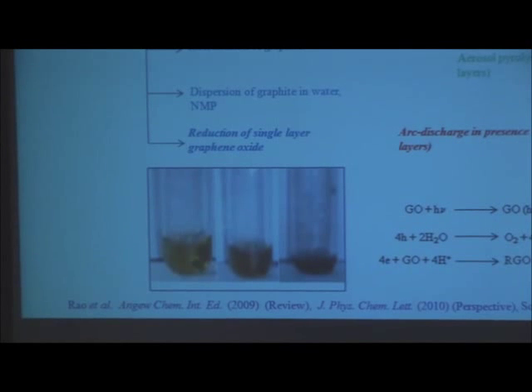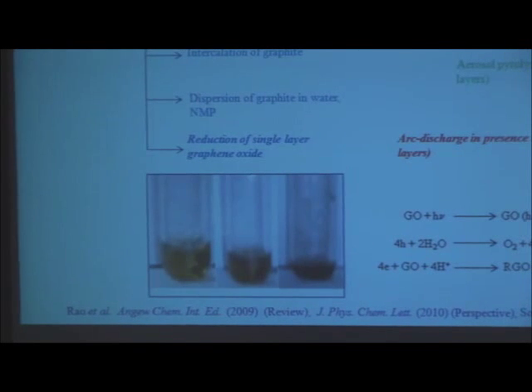It's all terrible. I didn't like it. So I was amazed when we found this one. What we find is you take graphene oxide, it's yellow, brownish yellow in color. We just put it in sunlight, it becomes graphene. In fact, sunlight is too slow, so you can use UV light, which is faster.